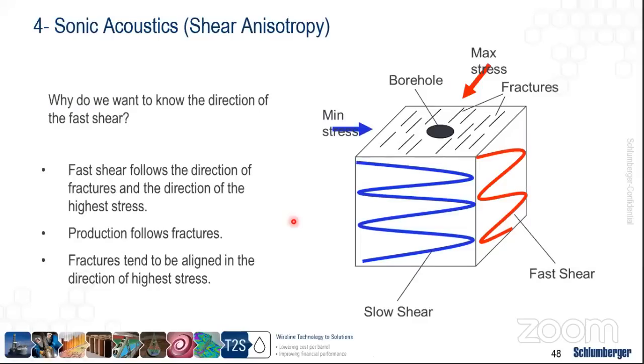So why do we need to know the direction of the fast shear? The direction of the fast shear is very important in order to understand the direction of the fractures, because the fractures would primarily go in the direction of the high stresses. And also it helps us to estimate and visualize the productivity of the well itself. Since the production would follow the fractures, which represent the highly permeable pathway, then if we have more stresses and more fractures in the reservoir, we estimate that there are more permeable zones, and this should contribute to more productivity.